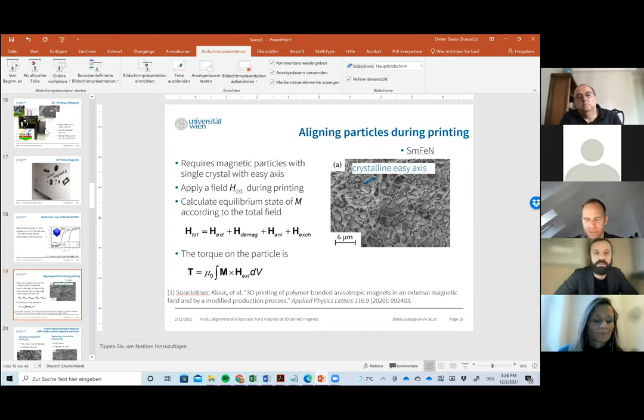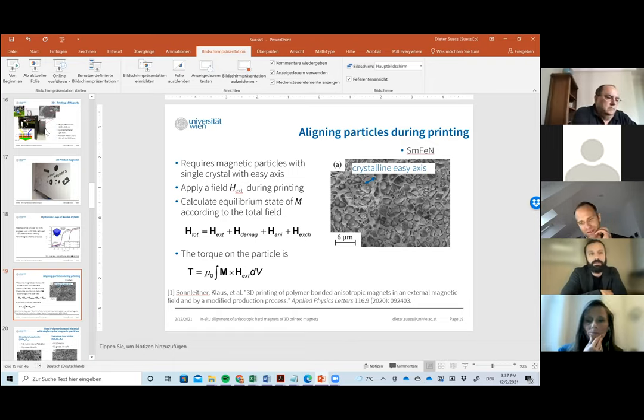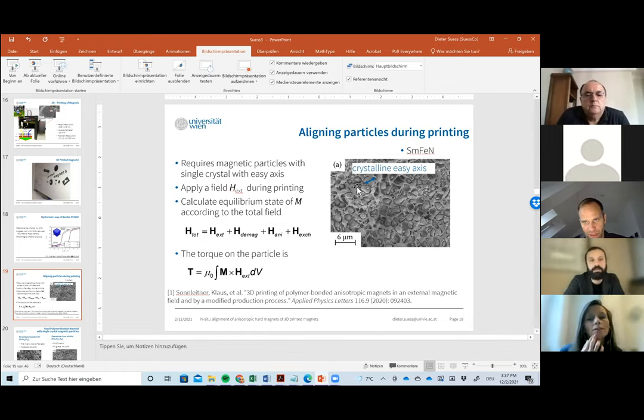It's a very good question, but I think the lateral resolution is determined by the nozzle diameter, and this nozzle diameter is determined by the fluid behavior of the polymer. If you make an even smaller nozzle, you can't print it, even if you don't have any magnetic particles inside. Even just a polymer filament can't be printed with a nozzle which has a very, very small diameter. So the magnetic particle is not necessarily the limiting factor for the lateral resolution for fused filament fabrication.